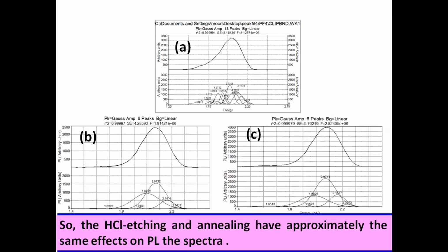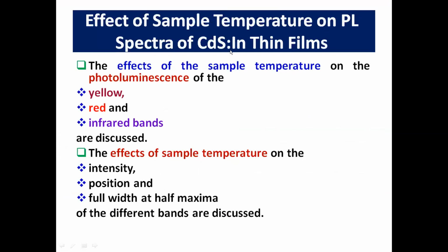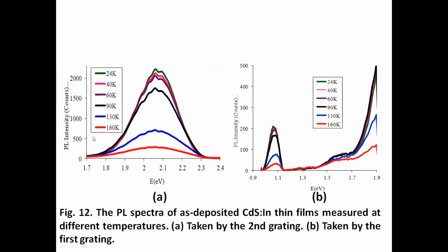Now we study the effect of sample temperature on the PL spectra for all bands, and for intensity, position, and full width at half maximum. Here are the PL spectra at different temperatures from 24 Kelvin to 160 Kelvin. You see the PL intensity decreases with increasing sample temperature. This occurs in the whole energy range for A and B in the figure.